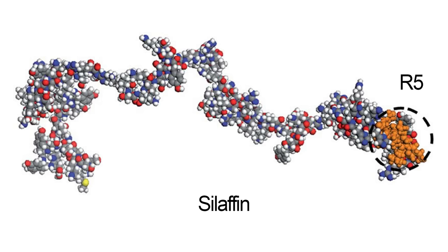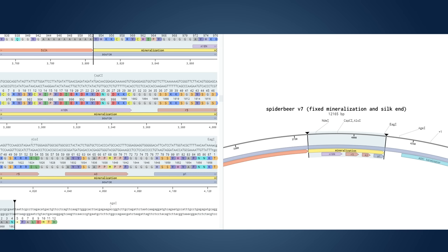These short protein fragments are called biomineralization peptides, and literally hundreds have been identified for a huge variety of minerals, metals, and other materials. I chose 4 peptides that should each bond to one of 4 different materials and strung them together with an inert spacer between them. This will give them a little bit of wiggle room so as to not damage their individual functions. This small chunk of biomineralization peptides was added to the very end of the silk gene, and then the whole plasmid was sent off to the company to be made.